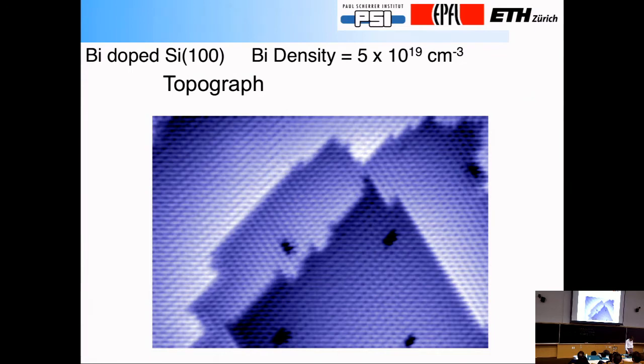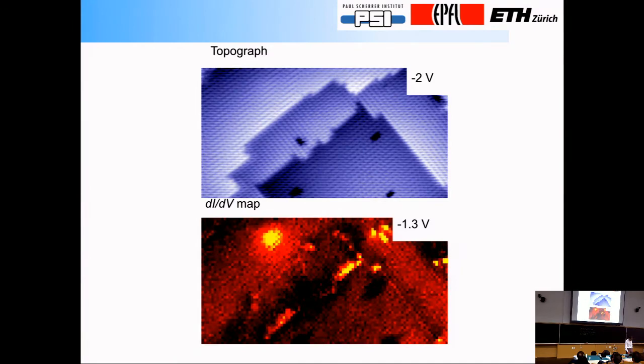And what you see here is essentially a topograph. Now with STM, of course, in addition to topography, you can also do density of states measurements. Those density of states you measure by parking the tip at each point on the surface and then measuring an IV characteristic, a current voltage characteristic. And the derivative of that current voltage characteristic gives you a density of states. And that dI/dV map is actually perfectly lined up with the topographic map. And what's interesting here is this topograph just shows nice ordinary steps.